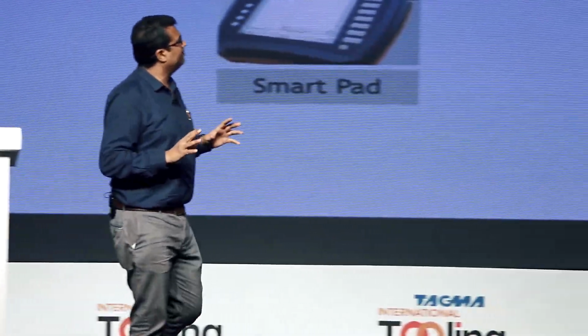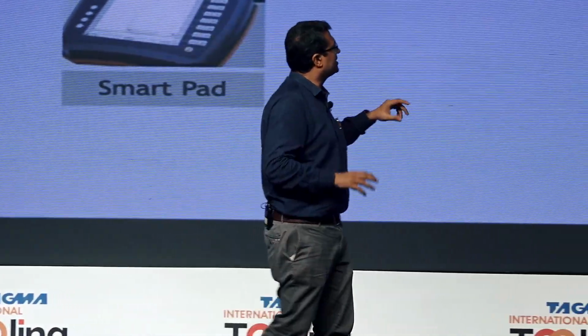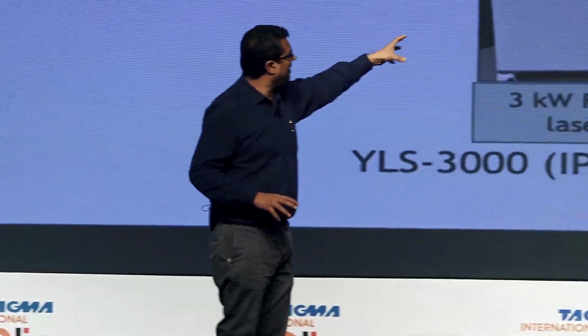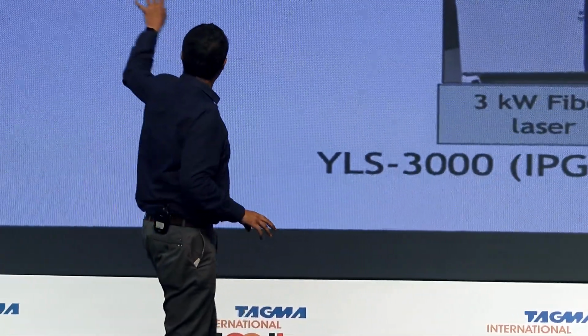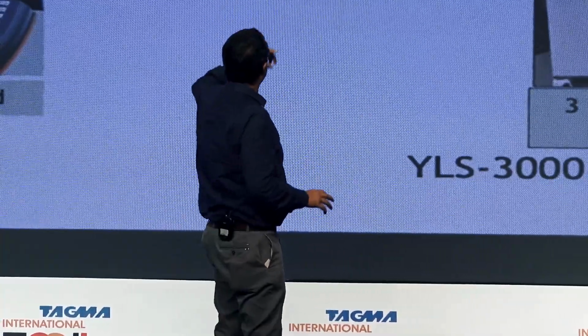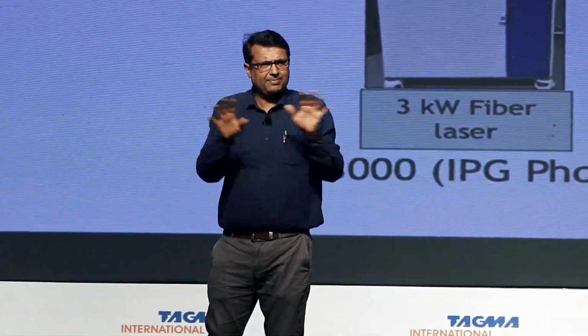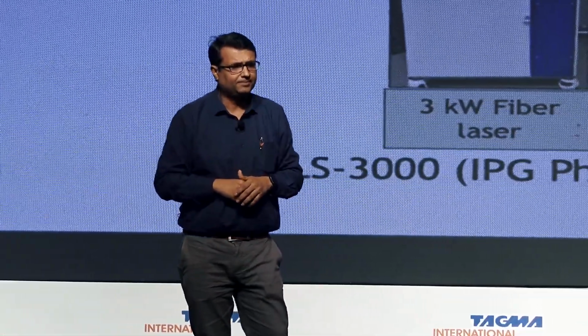This deposition system has a robotic manipulator, a deposition head, a 3 kilowatt laser, and also a powder feeder to feed the powder particles. You can have either a powder feeding system or a wire feeding system; we have both in the lab. Wire feeding is a new thing which we are still developing, but the powder feeder is fairly matured. We have done a lot of work with powder feeding systems. And then I'll show you a small video of how it works.